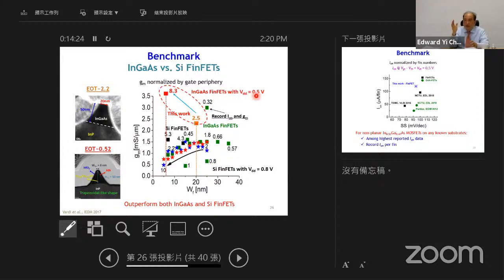Okay, so with the reduced bias voltage, that means we save more energy, but we still get very high on current. That means the speed is even much higher. Okay, and the GM is really high. So for this device, we present with the EOT 2.2 and the surface treatment. We use the high K. Actually, our device outperforms both InGaAs and silicon FinFET in terms of the current and also the bias voltage. Okay, and SS and the DIBL remain very low.